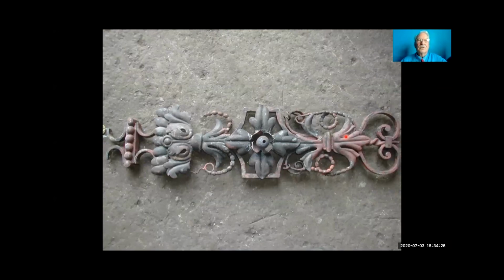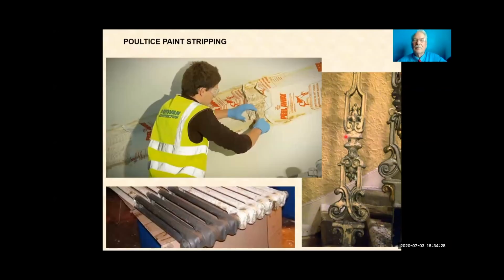I mentioned poultice stripping with a gel. We do use this quite widely. It's very good on site. Actually, we usually use a specialist subcontractor to come in and do it. They know how long to leave the material on. You put on a gel, then you put on the coating on the outside, which is just paper of some sort.